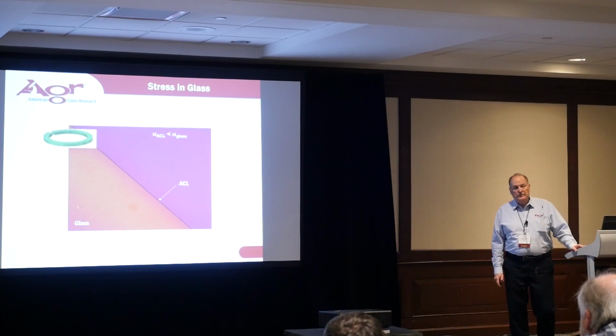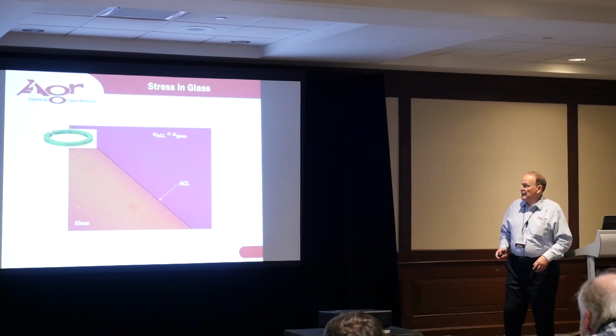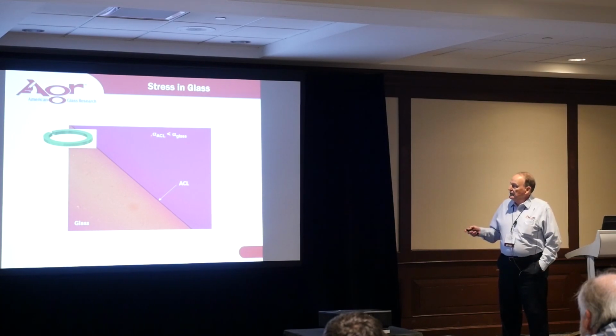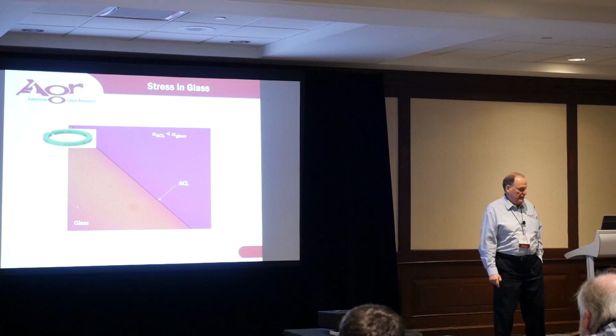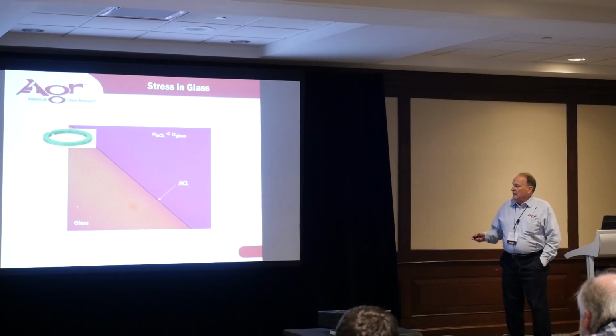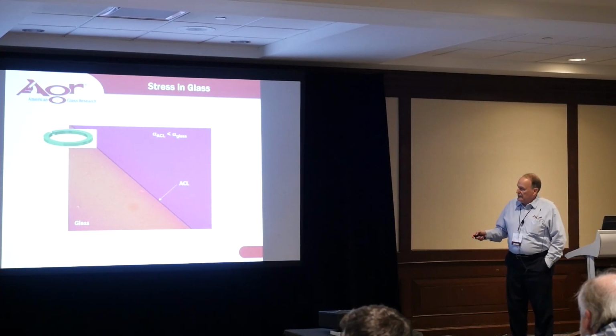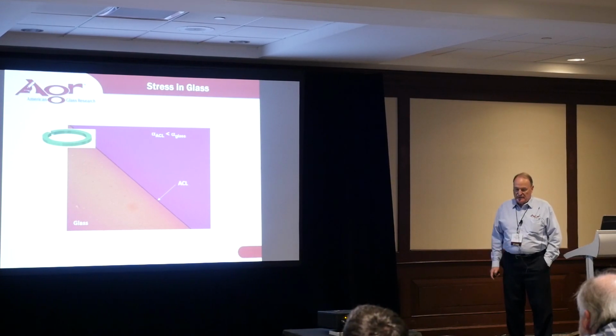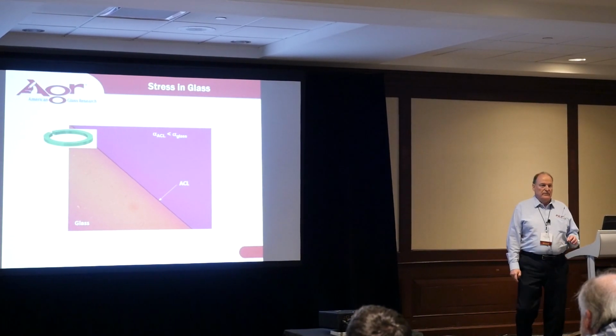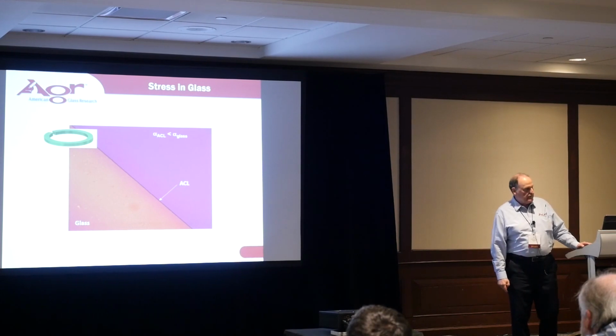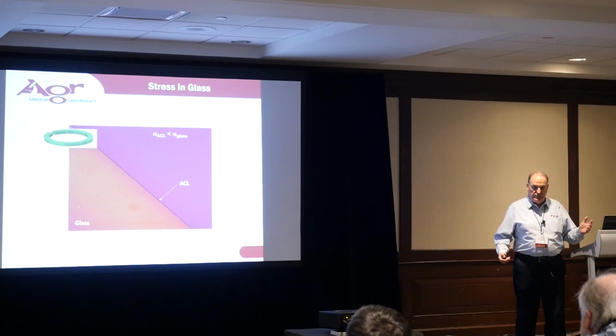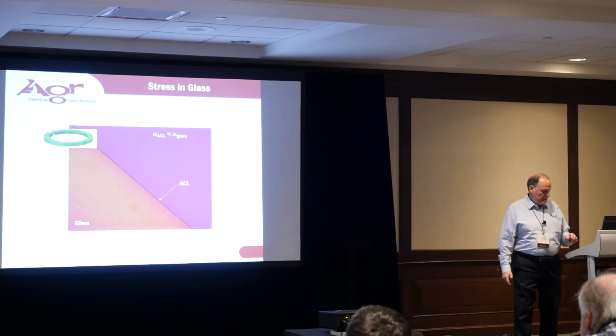Here's a view, exactly the same setup, except now the coefficient of expansion of the ACL is less than that of the glass. The orange color here is indicative of a tension stress in the glass surface. And once again, we can identify that stress and we can measure the magnitude of that stress. That's very easily done.